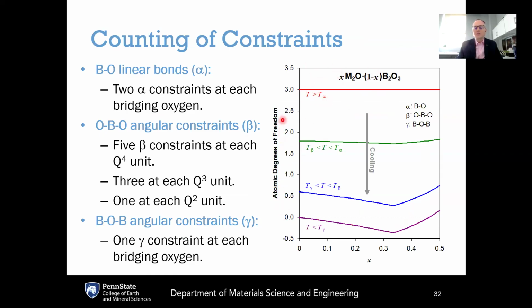This plot shows the atomic degrees of freedom versus composition, where the X here is the mole fraction of the modifier oxide, and then the different lines are showing different temperature regimes. And where we start is on the red line. The red line is at high temperatures that are above the constraint onset temperature for the strongest constraint. The strongest constraint in the system is the linear bond between the boron and the oxygen. And there are two of these alpha constraints, two of these linear constraints at each bridging oxygen. And so if we start at temperatures that are hotter than that, all the constraints are broken.